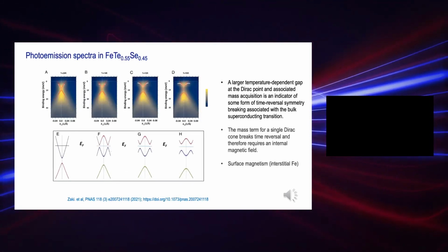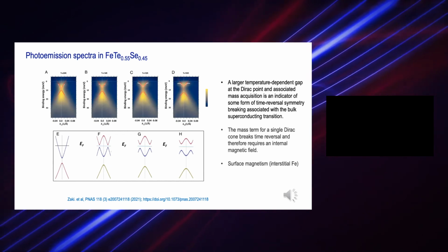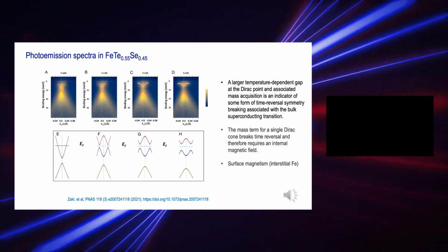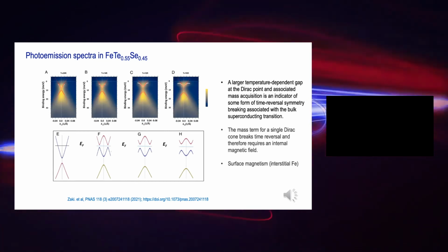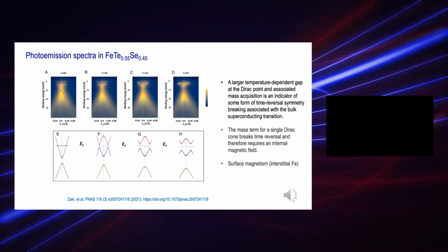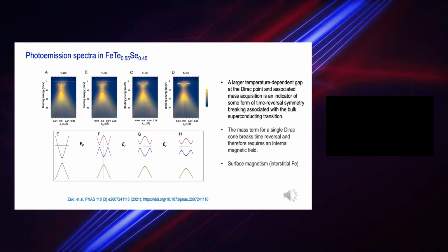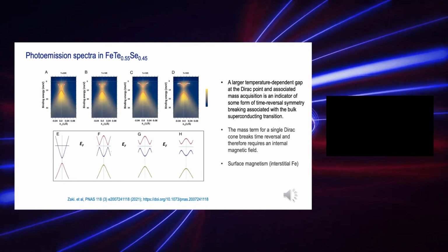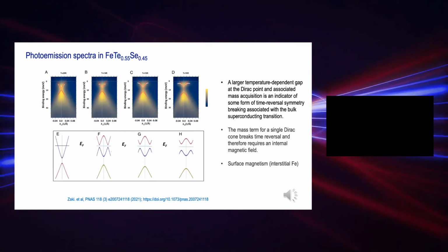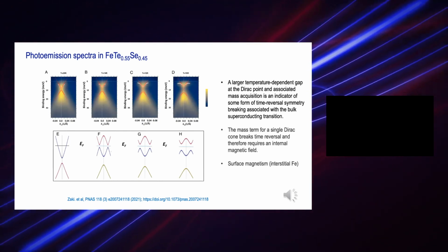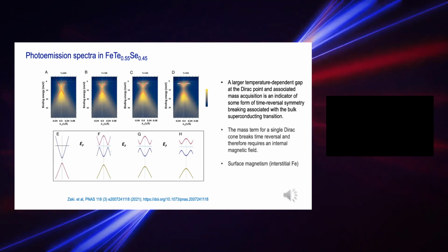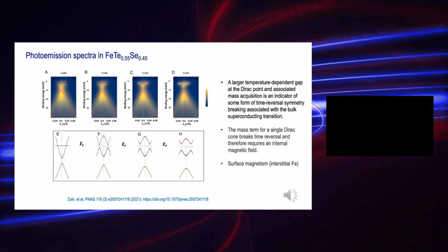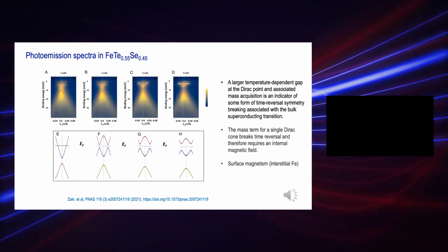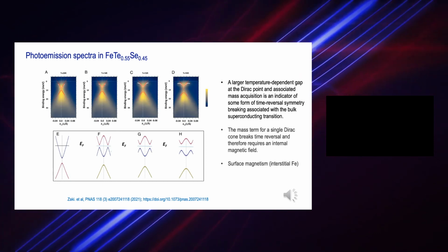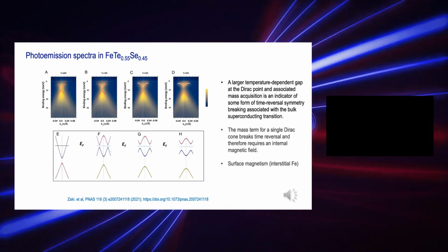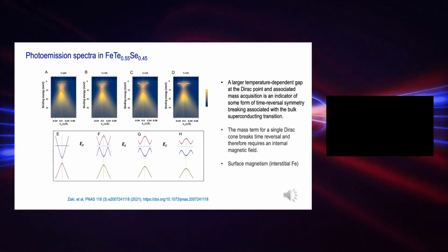The figures shown here are the results of electronic structures of optimally doped iron tellurium selenium, at 0.55 and 0.45 respectively, using angle resolved photoemission spectroscopy, ARPES. Figures A to D show the spectral intensity measured in the vicinity of the gamma point as a function of temperature: 20, 14, 12, and 10 Kelvin, respectively. Superimposed over the measured intensity, the white dotted curves show the peak intensity and the red dashed curve shows the underlying cone. Now, there are several interesting features that I want to point out here.